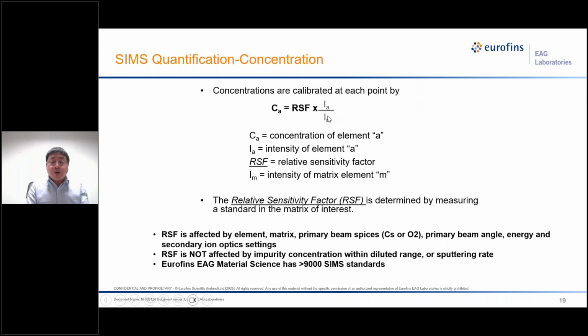So here is the concentration quantification. Basically, the concentration equals the relative sensitivity factor times the ion intensity of interest divided by the ion intensity of the matrix. The relative sensitivity factor is determined by measuring a standard in the matrix of interest. The RSF will be affected by the element, by the matrix, by the primary beam, by the primary beam angle, energy, and even secondary ion settings. But RSF will not be affected by impurity concentration within the dilute range, basically less than 1% atomic. EAG has more than 9000 SIMS standards, about 41 reference materials for silicon carbide.